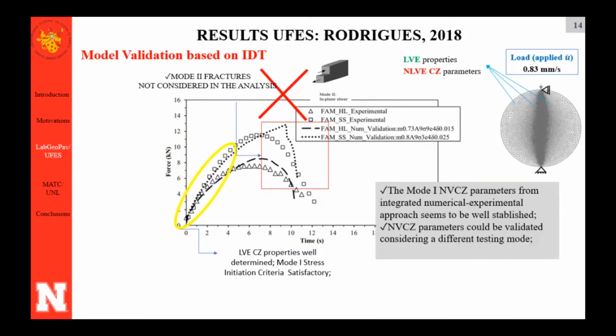So the mode 1 nonlinear viscoelastic cohesive zone parameters from the integrated numerical experimental approach seem to be well established. The results are fairly comparable between numerical and experimental analysis. The parameters could be validated considering different test modes. So we got the parameters from SCB and we validated with a different test mode, which was good.